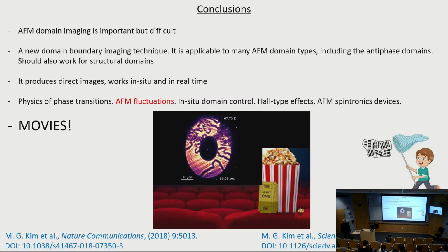Now, we believe they're not, actually, because what we see, the domain structure is very soft, right? So we can modify it by little thermal gradients. We can anneal the topological defects, right? So they're certainly not strongly pinned to whatever can pin them in the sample. Of course, structural defects may play their role in this case. In the case of the first images that I was showing, non-fluctuating domains, in the first sample, we saw some evidence of the magnetic domain boundaries pinned by structural defects, which we actually physically see on the surface. So that is also possible.